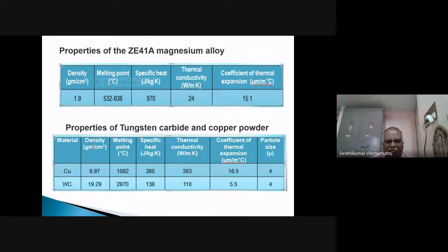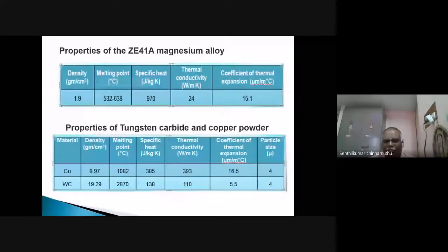The copper density is 8.97, the melting point 1082 degrees Celsius, specific heat 385, thermal conductivity 393, coefficient of thermal expansion 16.5 and a particle size of 4 microns. Similarly, the tungsten carbide, the density of tungsten carbide 19.29, melting point is 2870 degrees, specific heat 138 joule per kilogram Kelvin, thermal conductivity 110 watt per meter Kelvin, coefficient of thermal expansion 5.5 μm per meter degree Celsius, and the particle size is 4 micron.